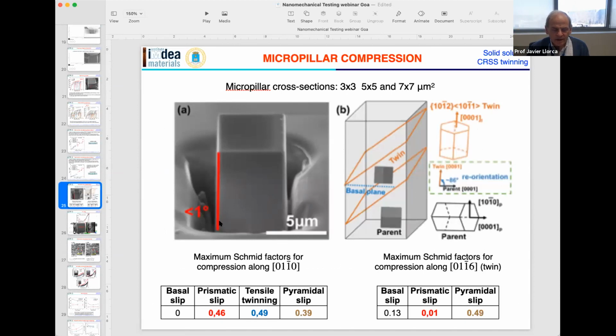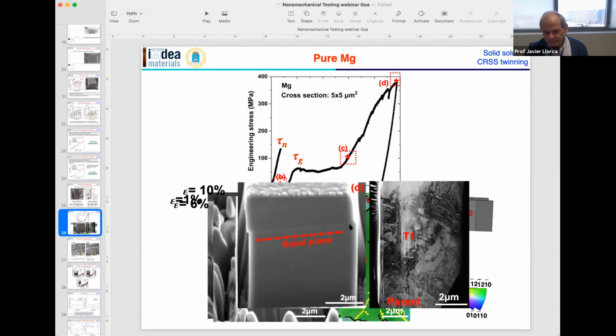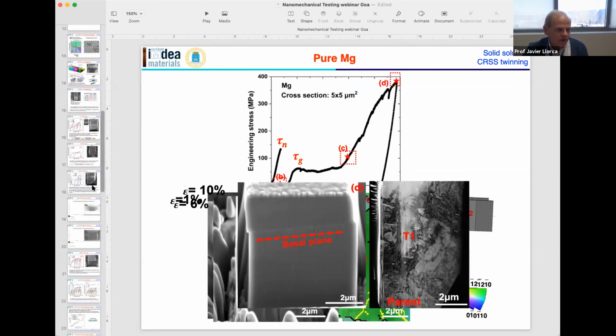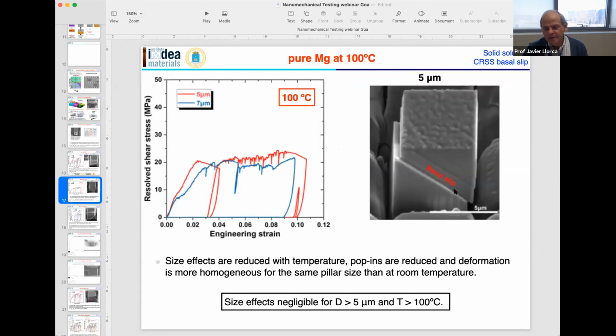The second good thing is that if you want to see the slip trace of the active deformation mode on the pillar surface, this is much clearer because it is a flat surface. From the viewpoint of identifying which slip system is operative, here you have basal slip, and when you come here, this is also basal slip. It's much easier with flat surfaces, as in square pillars. So these are the two reasons why we use square pillars instead of circular pillars.